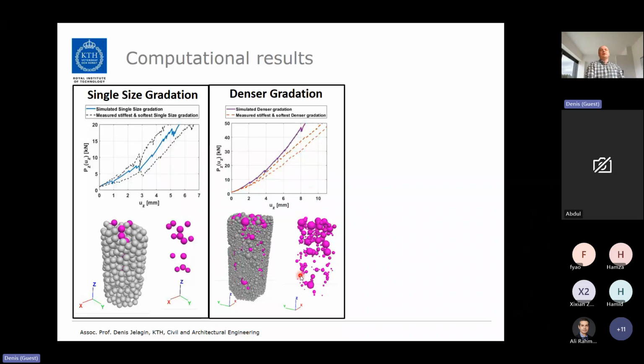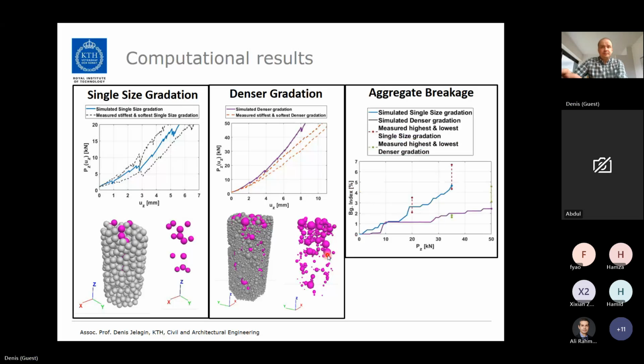One nice thing with discrete element simulations, which is kind of unique, is that you can also gain micromechanical insight into the processes in the material. You can, for instance, see which sizes break more within the material. Here we could see that the breakage process is dominated by coarse aggregate particles. And we can also compare the amount of aggregate breakage. Here we have the breakage index, the amount of deviation of the gradation curve before and after the test, and the solid lines are from numerical simulations. That's where we can see the full progression. Experimentally, we can only get a snapshot at certain contact load levels. We have one snapshot for single gradation at 20 kilonewtons and 35. And for dense gradation, we have a snapshot at 35 and 50 kilonewtons.